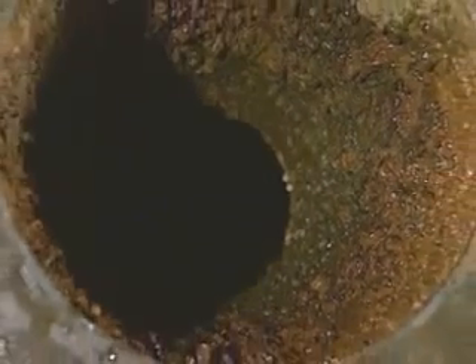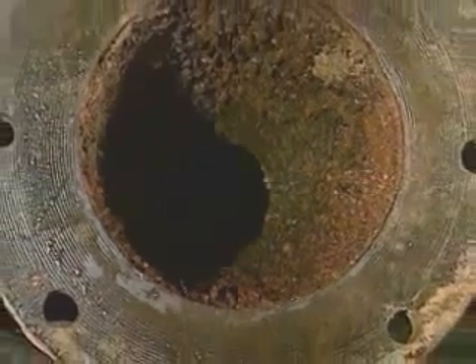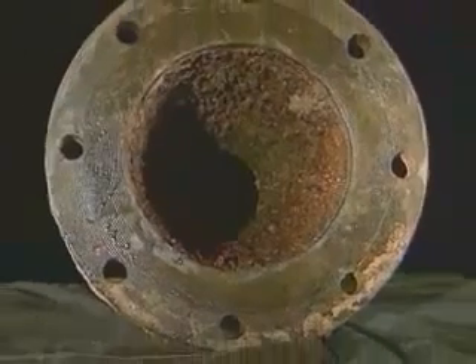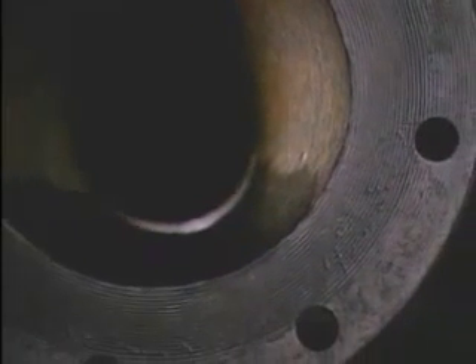Here we see a typical pipe which has been in distribution for a few years. This is nothing new or different than any other pipes in distribution. It is heavily rusted and tuberculated. We then ran Seaquest through this pipe, and as you can see, the pipe is now clean and devoid of any rust or tuberculation. The benefits of a clean pipe over a tuberculated pipe are obvious, but just to mention a few, you will have better flow rates, cleaner water, and less biofilm formations.